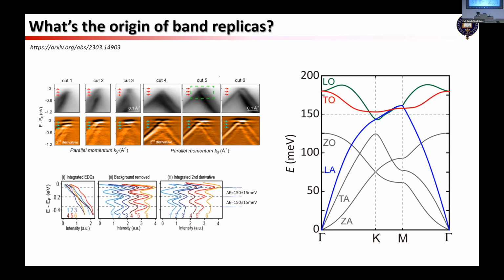Could it be of electronic origin? That's also unlikely, because for example Landau levels or other electronic correlations will not give you this evenly spaced replica band. The energy spacing will vary. So then we landed on the phonon, and there was no magnon to consider here, right?